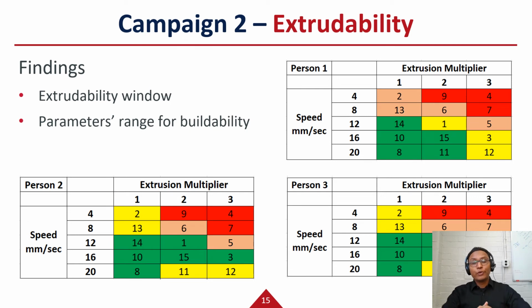All evaluations were performed by at least 3 individuals, and we took the average of it to mitigate any potential bias in the data collection. This campaign helped us to find the extrudability window for the material. Moreover, it narrowed down the range of parameters for our next campaign.